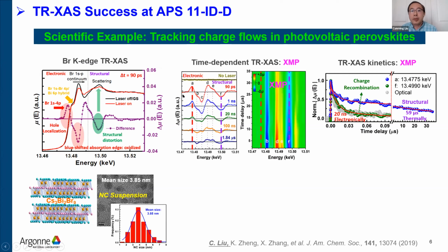The further time-dependent spectral and kinetics measurements show that the electronic relaxation, represented by the hole localization at the bromine site, can be much faster than the recovery of the structure distortion represented by this negative peak. One thing I want to point out is that this 2D TR-XAS spectrum is constructed based on our X-ray multiple probe data acquisition.